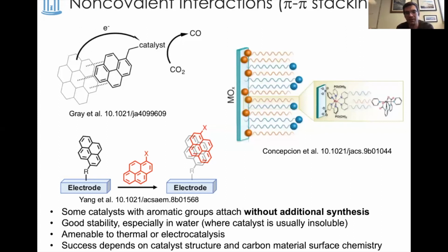Water is maybe the solvent where this is most commonly seen, and a lot of times that's because the aromatic-containing catalysts are not soluble in water, and so desorption is mitigated by the insolubility of the catalyst. But these approaches, in theory, can be used in a range of solvents so long as they're not forcing desorption by competing pi-pi interactions.